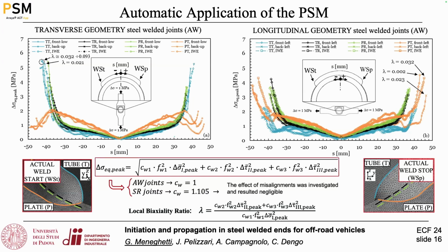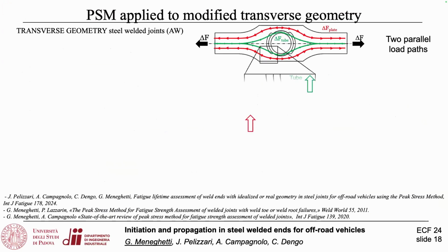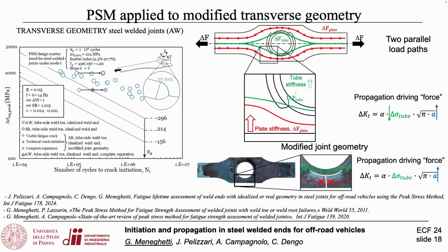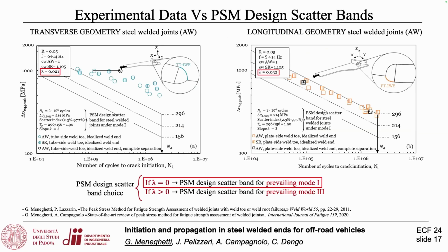After that, if we consider the distribution of the equivalent peak stress and the local biaxiality ratio, you see that we had in both cases a very low value, close to 0. So we adopted the design curve for pure mode 1, the one with slope equal to 3. Sorry, I went forth and I have to go back. Here we are. This is the situation for the transverse joint geometry. This is the situation for the longitudinal joint geometry.